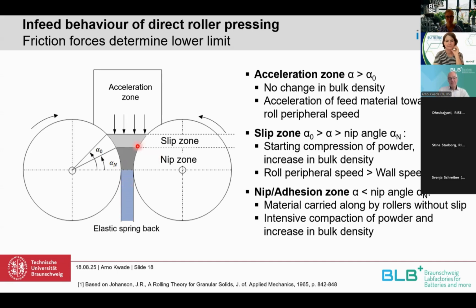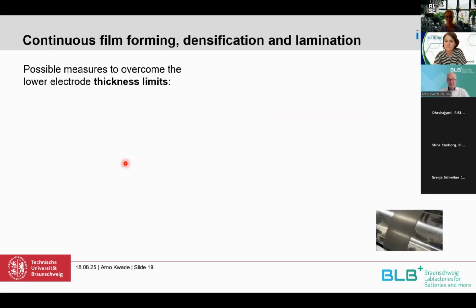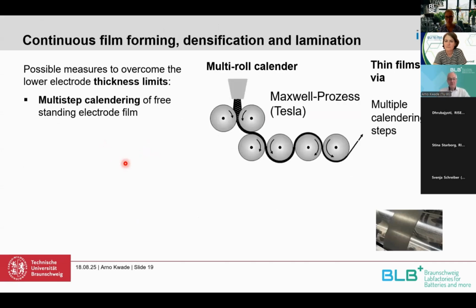But the question here is really the wall friction angle. If the wall friction angle is high, then you have this nip zone very early and you get a lot of material which you have to compress, and then you automatically get a thick electrode, or the torque of the rollers is maybe not sufficient anymore to form the film. So that means low wall friction angles are advantageous to get thin films. This we can also see later, but first of all, the question is how we can get thin films.